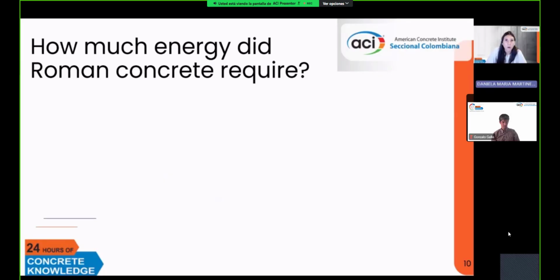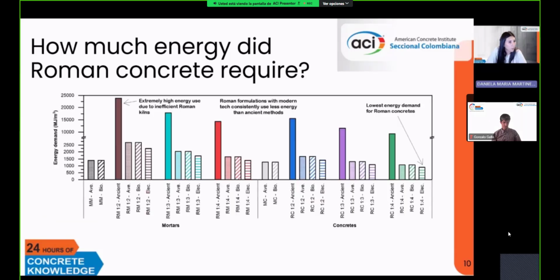So then, how much energy did Roman concrete require? Many people assume that lower temperature production automatically means lower energy demand. Surprisingly, that was not always the case, as we can see in this bar diagram, where we're comparing energy demand on the vertical axis and the different formulations that we studied, the Roman concrete and mortar formulations across different production scenarios, compared to the modern counterparts. The modern counterparts we can see here: modern mortars are these gray bars, and modern concretes are these other gray bars. The rest of the bars correspond to Roman concrete formulations, the 1:2 ratios, 1:3 ratios, 1:4 ratios, and it will vary depending on the production scenarios and the technology used for production.